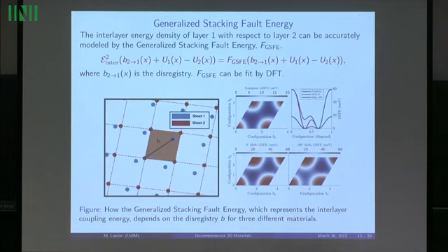And it also has some symmetry. There are two energy-minimizing states, like BA and AB. You have the same thing in 0-degree molybdenum disulfide. If you take one layer and rotate it by 180 degrees, it's very interesting: you get something that's not symmetric. So you get this kind of energy landscape, and that has an impact on the actual relaxation patterns we see.